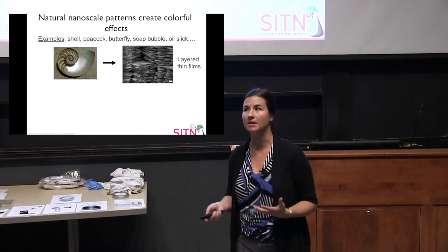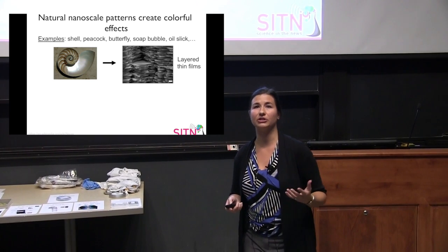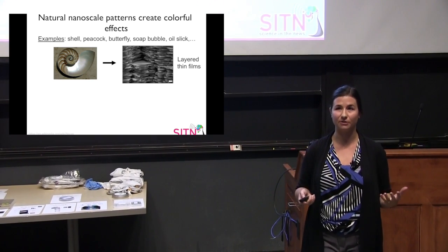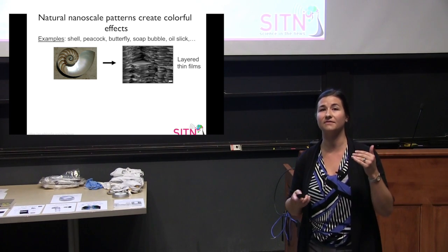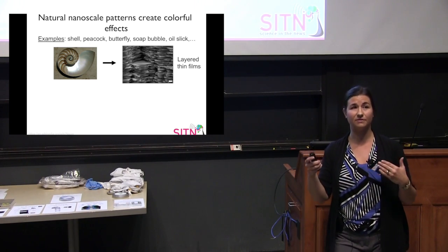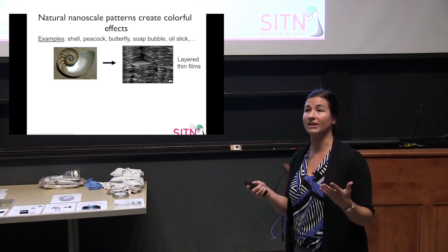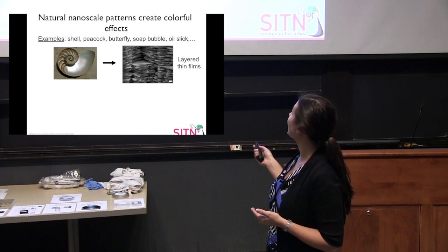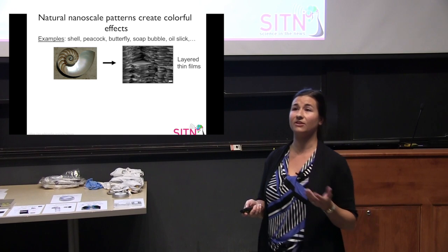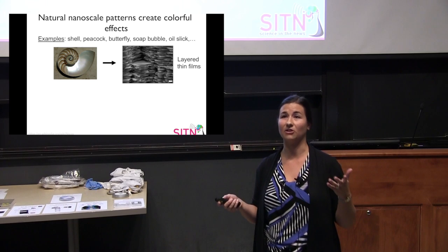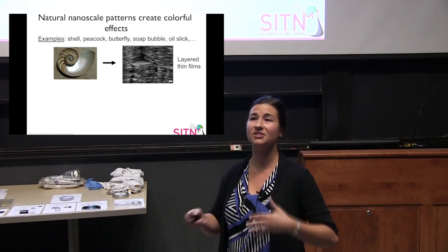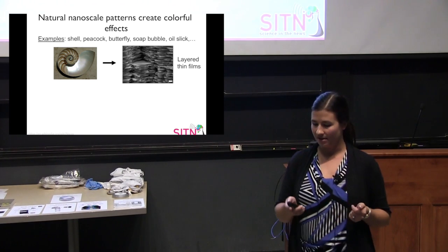So what's happening? Well, Andy mentioned earlier that we have this thing called thin film interference, where if you put in light, you can have a thin film that can constructively interfere and allow you to reflect certain colors of light. What we have here is a whole bunch of different layers that are all different thicknesses, and when we put in light, they all reflect different colors. So we just end up with this white, shiny looking material.